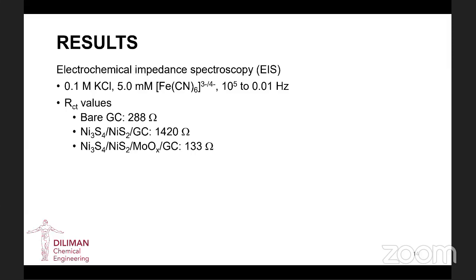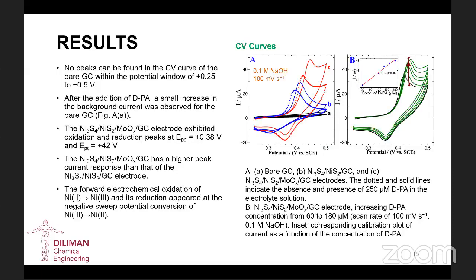So in this case, you can see that the last material with molybdenum oxide has the lowest RCT value, meaning it has the highest electron transfer rate among the three materials listed here. And then we conducted